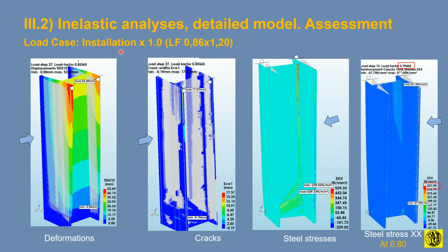If we look at the installation phase now, unity, because there is a load factor of 1.2 at 86%, we do have this model deforming at 50 millimeters, fixed here in the chamber, and the crack widths are already now up to 17 millimeters. But look at the crack widths. We can see that the crack widths are developing over not just the full height of the exposed wall, which already started cracking during the loading phase, but all the way up.